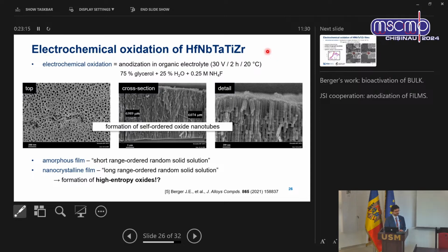samples. We needed one without some elemental separations, so we couldn't use the high temperature grown. We have to use either the amorphous film, which has short range order but no separations of atoms, and also this nanocrystalline film, the finest one, and see if we can produce the high entropy oxides.